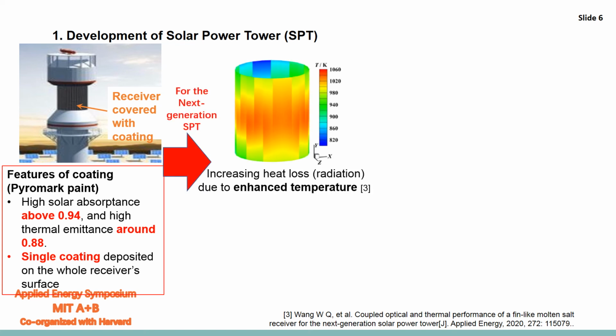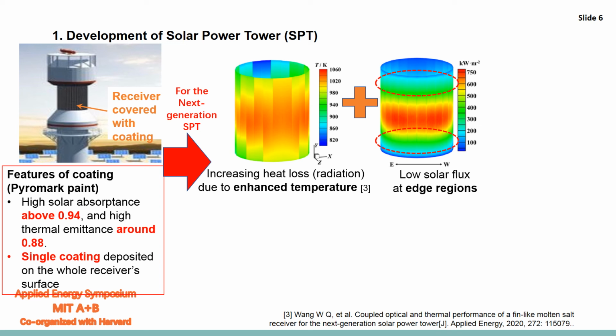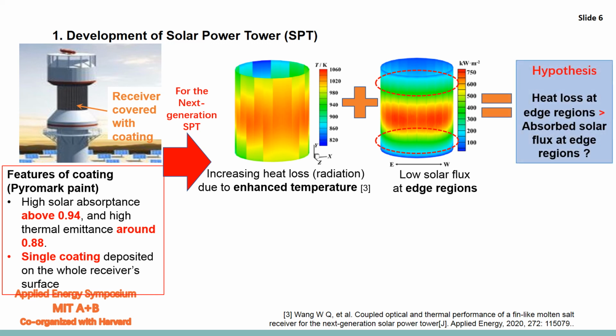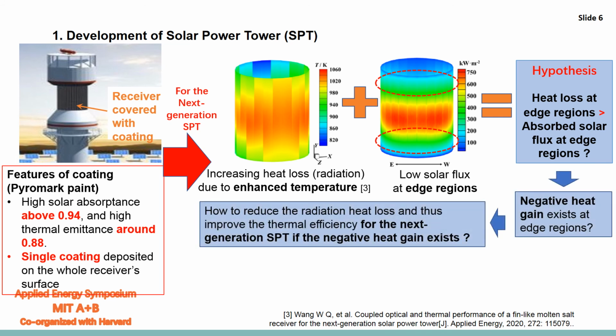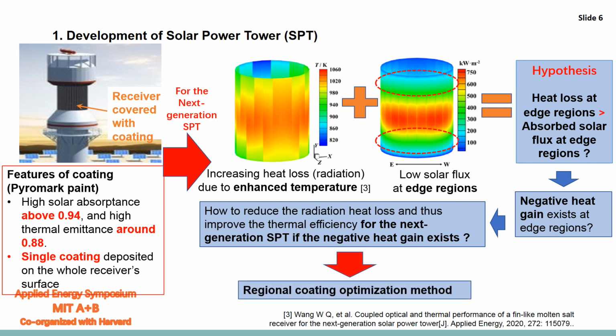For the next generation SPT system, higher temperature and high thermal emittance of the coating will cause higher heat loss, mainly radiation heat loss. As mentioned just now, the edge regions of the receiver surface have low solar flux. Considering high heat loss and low solar flux at edge regions, we thereby proposed a hypothesis: whether the heat loss at edge regions is higher than the absorbed solar flux. If so, that means the negative heat gain of tower receiver will exist at edge regions. In this context, how to reduce the radiation heat loss and thus improve the thermal efficiency for the next generation SPT? If the negative heat gain exists, then we will introduce the regional coating optimization method to solve this problem.